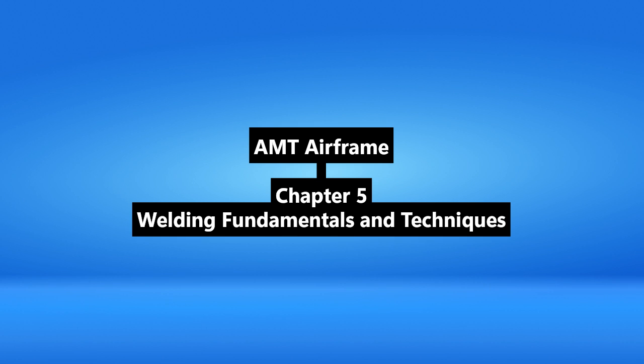But post-weld tempering, stress relief, is highly recommended. TIG cools fast, can cause brittleness. Heat the whole weldment evenly to 1100, 1200 F, dull red, after it cools. Hold briefly, let cool slowly. Right. If using 4130 filler, preheat and post-heat are even more critical to avoid cracking. Always consult engineering specs for critical parts.